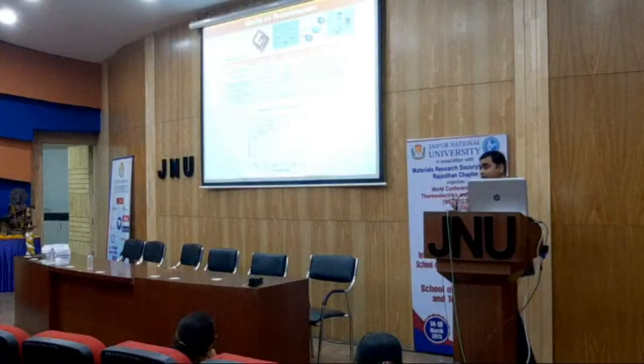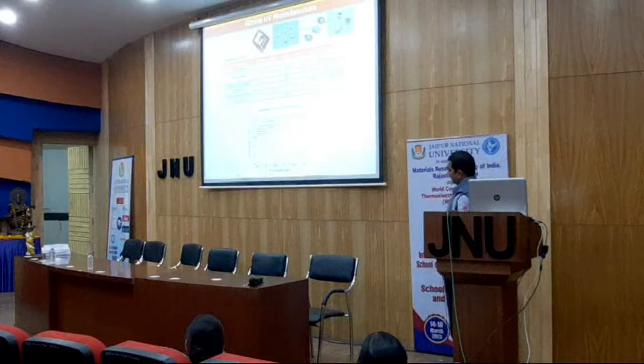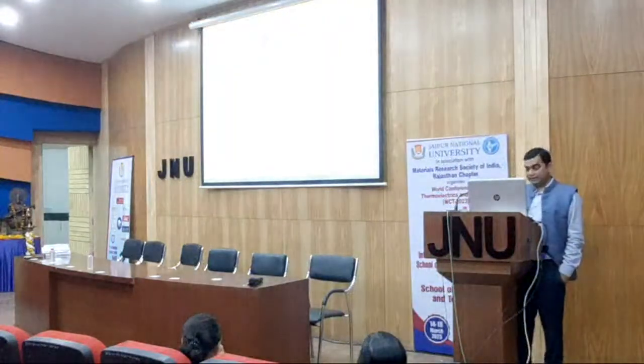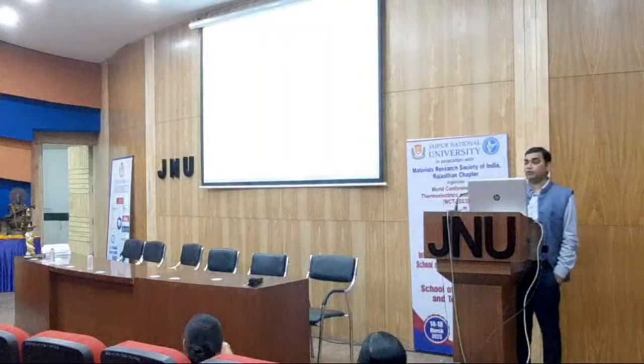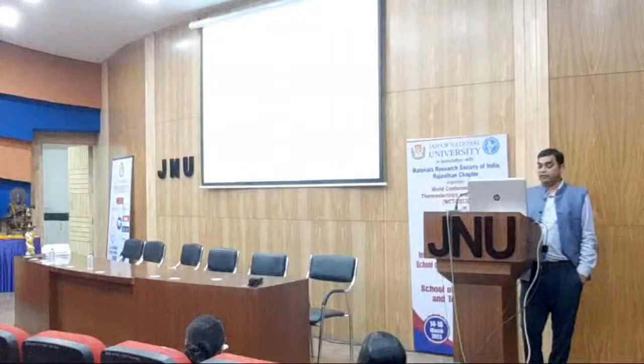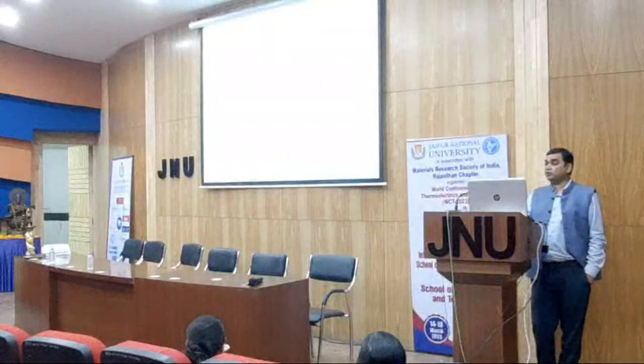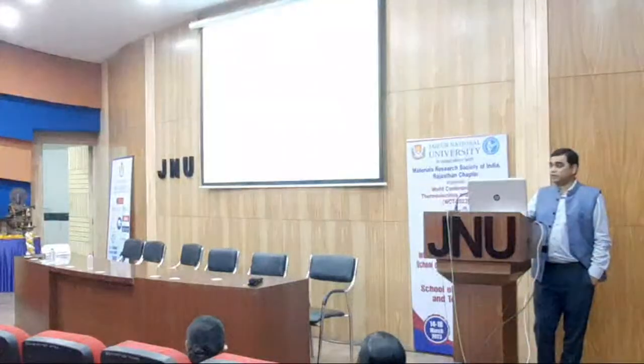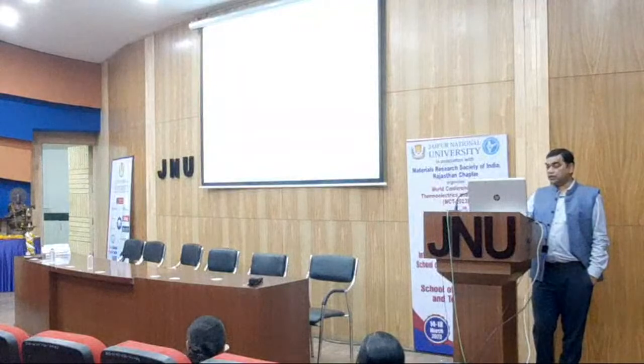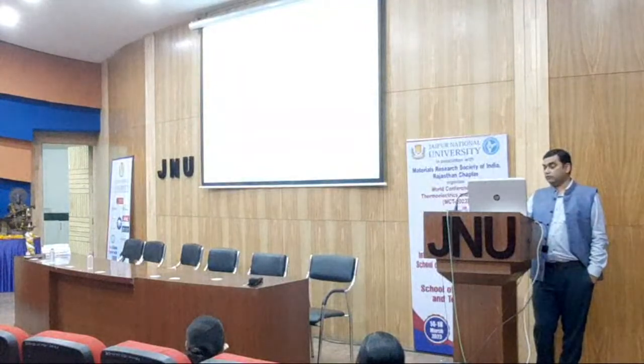However, nitride-based optical detectors are in the initial stage of development. There are a few where responsivity is not that great, so we have started working in this area. These are the research activities of my group at CSIR National Physical Laboratory. We grow epitaxial gallium nitride films, nanostructures and heterostructures by plasma-assisted molecular beam epitaxy, which is one of the highly sophisticated techniques to grow any epitaxial thin film across the domain.